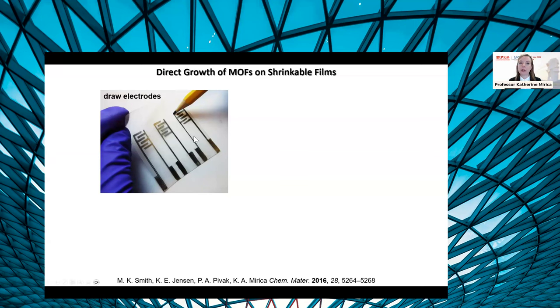One, the use of a shrinkable polymer film allows us to quickly, rapidly, and inexpensively fabricate interdigitated electrodes with patterns that can be obtained after shrinking this pre-stretched polystyrene into highly miniaturized, millimeter-scale form factors that would be difficult to draw by hand, but we're using a very straightforward fabrication technique.